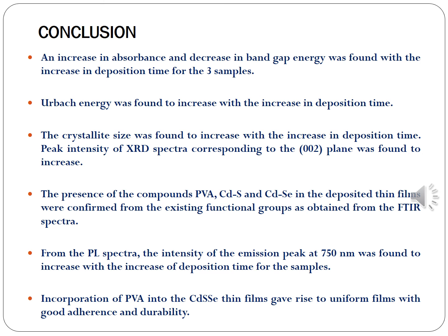And finally, the conclusion. An increase in absorbance and decrease in bandgap energy was found with the increase in deposition time for all the samples S1, S2 and S3. Urbach energy was also calculated and it was found to increase with the increase in deposition time. From the XRD analysis, the crystallite size was found to increase with the increase in deposition time. The peak intensity of XRD spectra corresponding to the 002 plane was also found to increase.